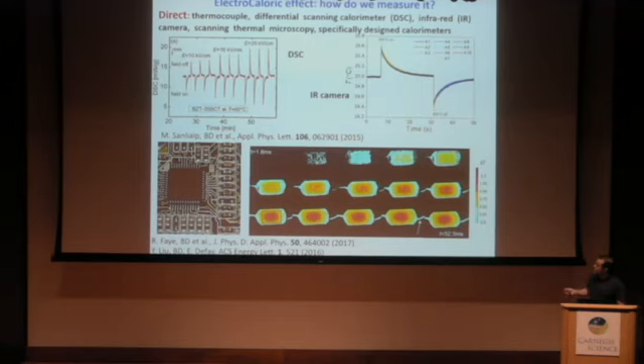For instance, you can use calorimeters. Then you apply electric field. You have a heat flow here. You switch off the field. You have an endothermic heat flow. You can also use an infrared camera, which is very nice because you can then have a view of the heat extracted from your system. So this measurement, for instance, has been done by Romain Fay. He just took an MLC capacitor here. You have them in your laptops. And applied the electric field,